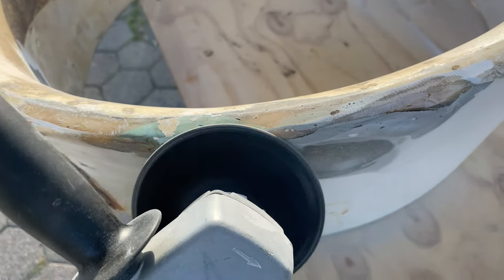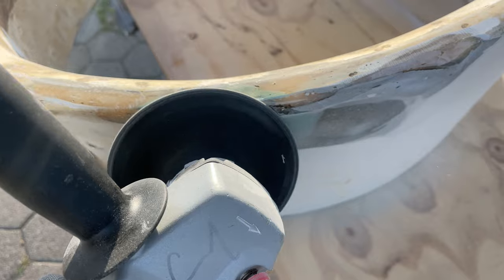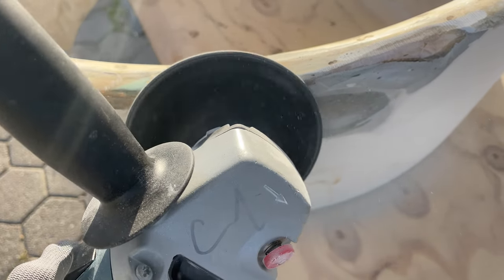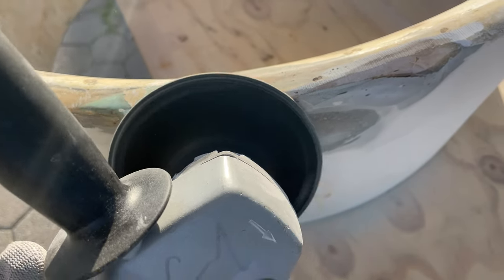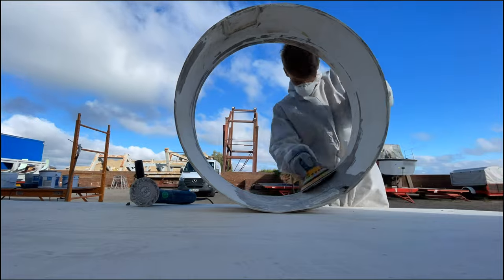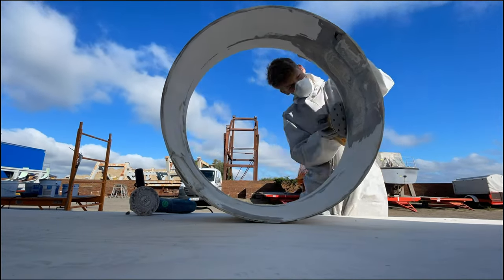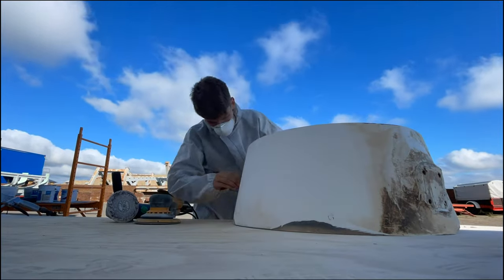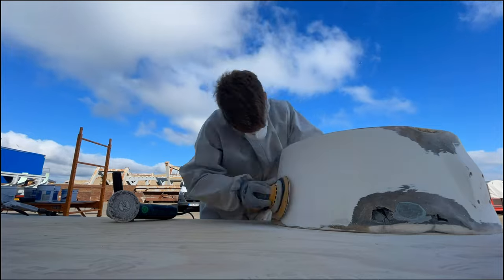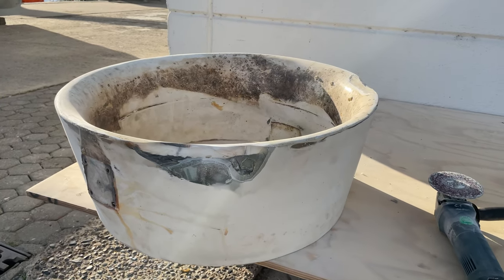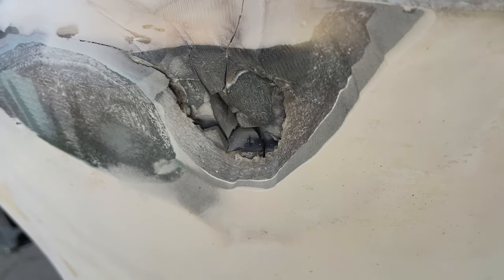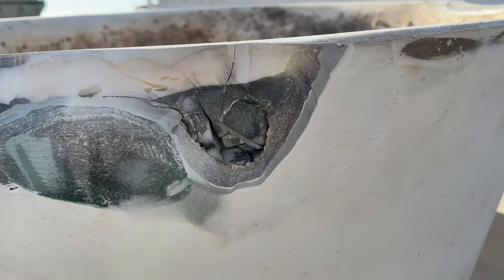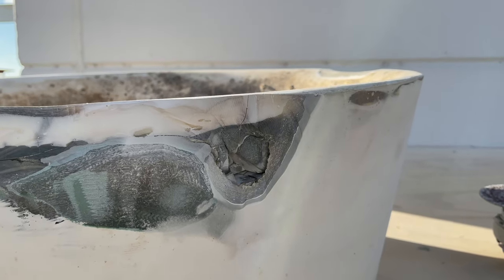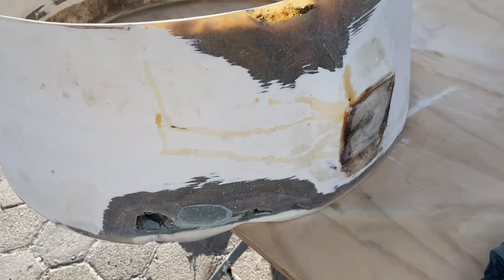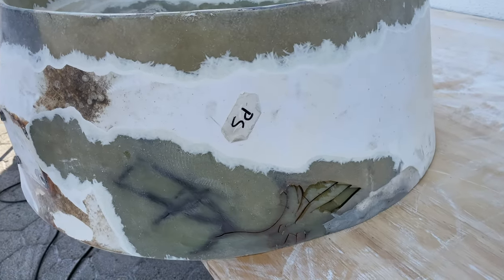The first step was to use an angle grinder to grind open all the damages, to get to the bottom of all the cracks, and then to sand down even more so the fiberglass is visible and all the gel coat is removed. That proved easier in theory than in practice, because once we started grinding down all these things, we found that it's actually not a classical fiberglass piece, but a fiberglass shell that was filled with resin in production. That resin in some places was missing completely, so that you had a hollow shell to work with. If you keep grinding that, then there's no nozzle left after all.